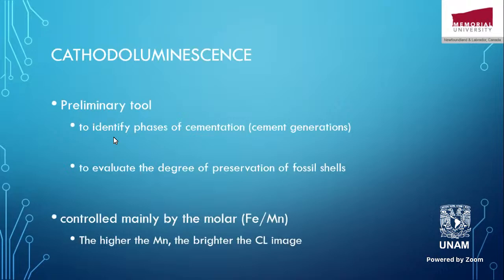We look also at the cathode luminescence of the carbonates because this is a good tool for identifying generations of cements. The basic concept of cathode luminescence is we hit the carbonate cement with an electron beam under vacuum, and this excites the electrons in some of the elements replacing the calcium in the calcite crystal. This makes the electrons jump to a higher energy level in the atom, but the electrons do not stay that long there. They come back to their ground state and lose the energy they gained when they got excited.